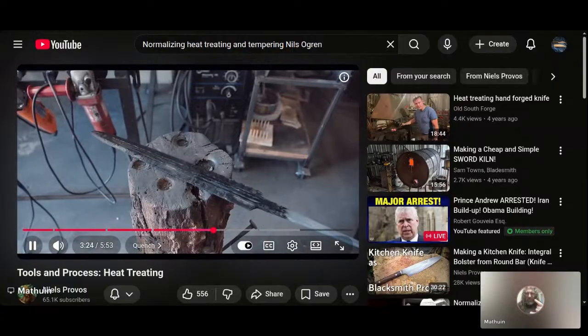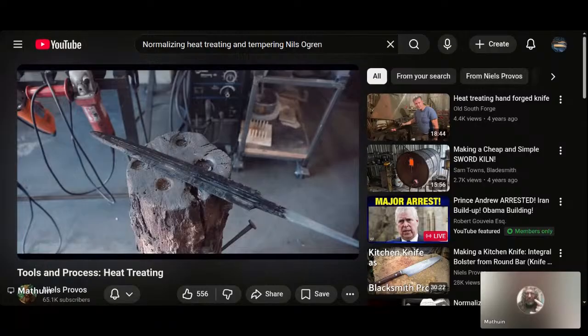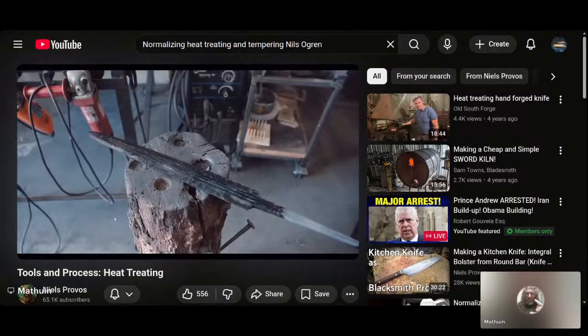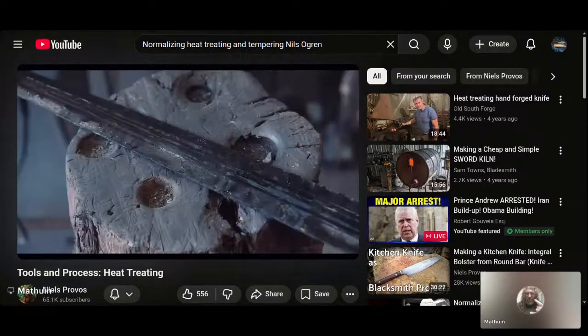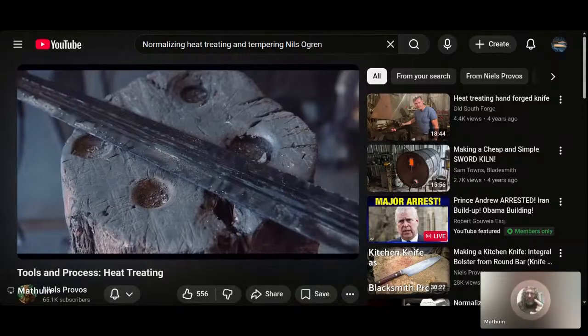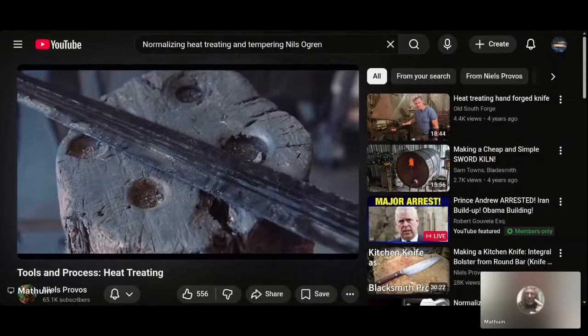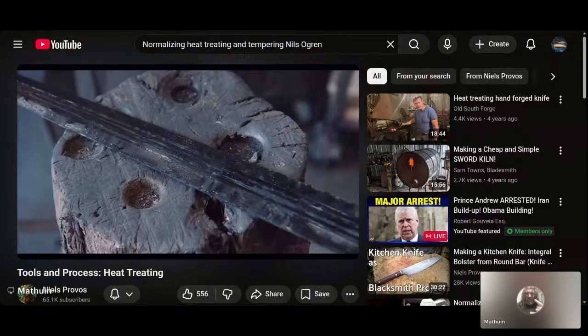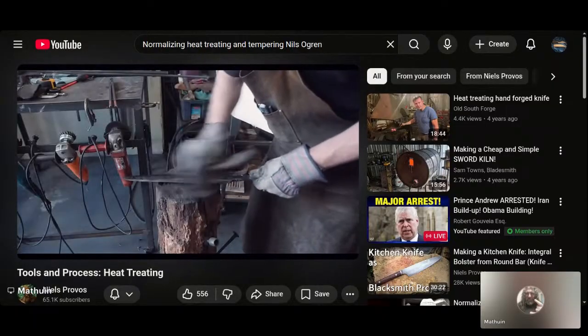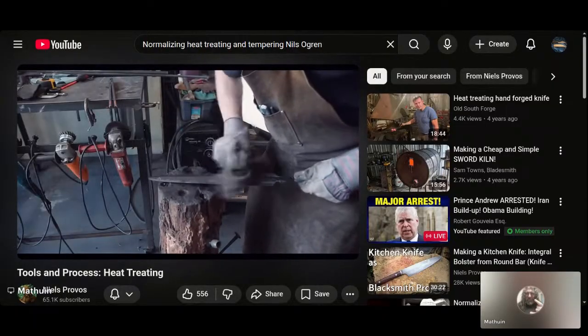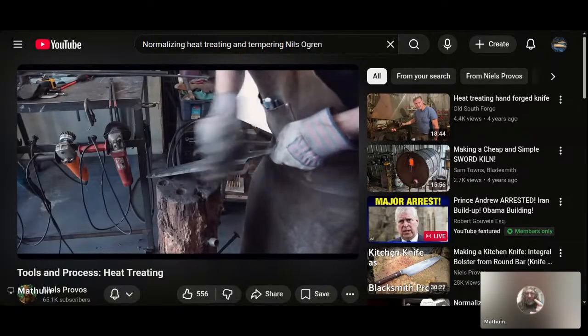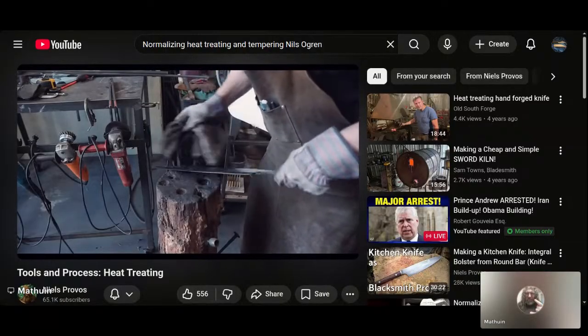After quenching, the blade is brittle, but the pattern is so much more visible. If the blade has been ground unevenly, heated unevenly, or quenched unevenly, it may develop a warp and as a result may no longer be straight. However, I will show you a trick that you can use during tempering to straighten the blade. Before we go there, let's quickly check the hardness with a file.